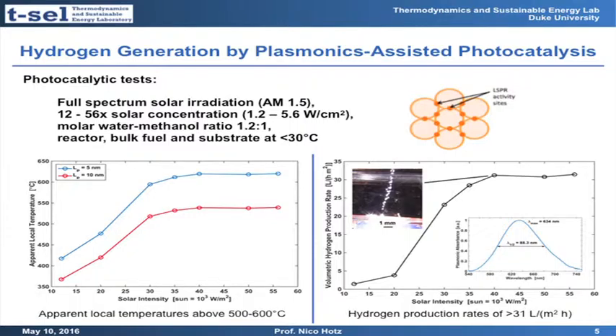With that, we can achieve hydrogen production rates of 30 liters per hour per meter square, which is pretty good considering that we actually only use these small spots. About only 1% of the whole substrate is at the moment usable. If we can find ways to increase the surface utilization, we can achieve much higher gas production rates anyways.